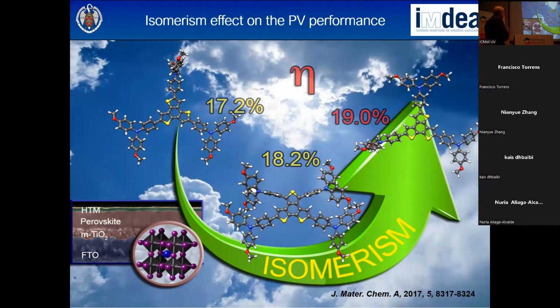But look, just by playing with the isomerism in the same molecule, the position of the sulfur is not innocent. We consider that when you have 2 sulfur atoms pointing in the same direction, you are improving the efficiency, because now you increase 1 point to over 18. This one is symmetric, but when you break the symmetry it also has some importance. So we reach 19% efficiencies with these molecules.